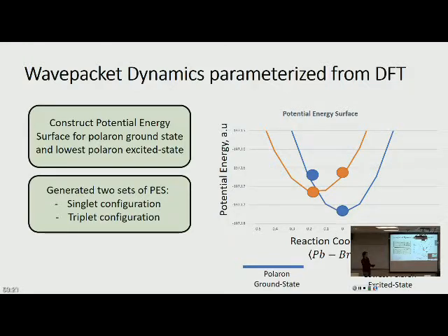And then with the same electronic structure, we just use the ground state geometry to get this point, because since this is the reaction coordinate, it's the same geometries. And then we just do the reverse for the ground state. So we do the excited state geometry with the ground state electronic structure. And that's how I made these parabolas for the potential energy surfaces. And then I did two sets, one for the singlet spin configuration and one for a triplet, just to have a reference when doing these calculations. Then what I found is that for the triplet, the change of geometry is lower compared to the singlet.